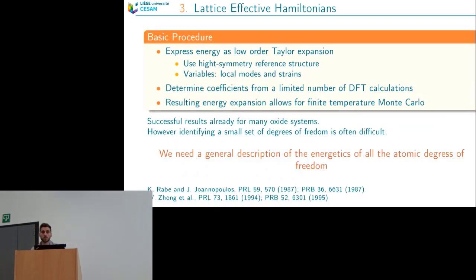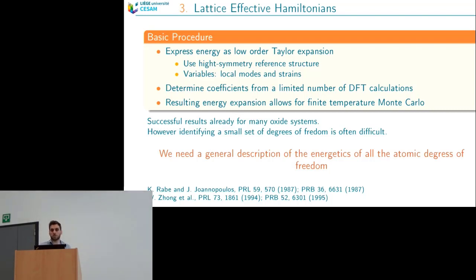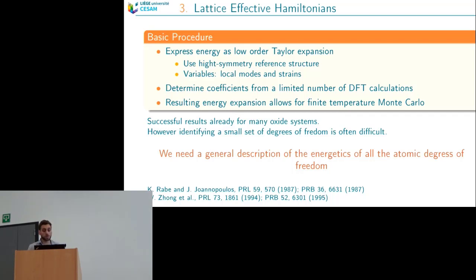Focusing now on the lattice effective Hamiltonian: the basic procedure was to express the energy as a Taylor expansion using a high-symmetry reference structure, select a few modes to study along with the strain, and determine the coefficients. Once the effective potential is built, you can run any dynamics to explore the energy surface. Previous results were successful, but required identifying a small set of degrees of freedom in advance.